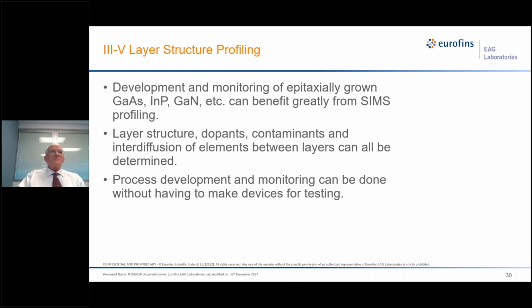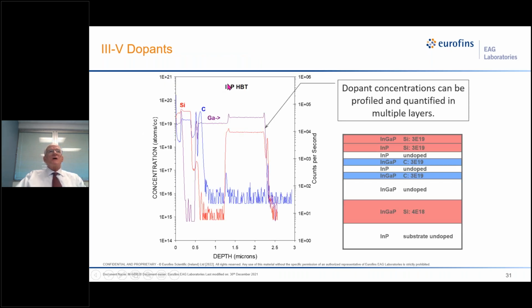So, multi-layer structure profiling. Development and monitoring of epitaxially grown layers greatly benefit from SIMS, and we can determine layer structure, dopants, and all these good things, and a lot to help with process development. Here's an example of an indium phosphide heterostructure bipolar transistor where we have this structure over here. And we can monitor the major elements, the gallium here, two different gallium levels are here. When you get to the indium phosphide, the gallium drops off. Carbon doping here and here, and silicon doping here, and this top layer here is the InGaP.